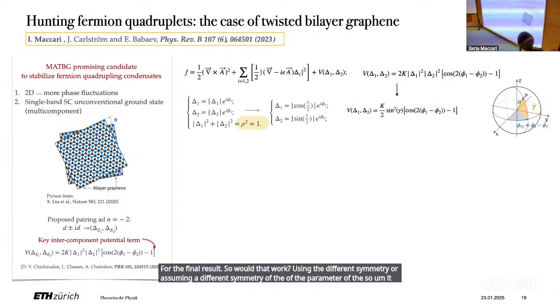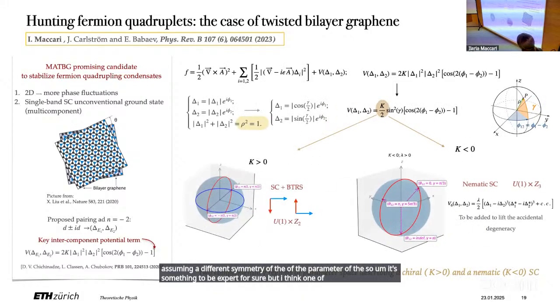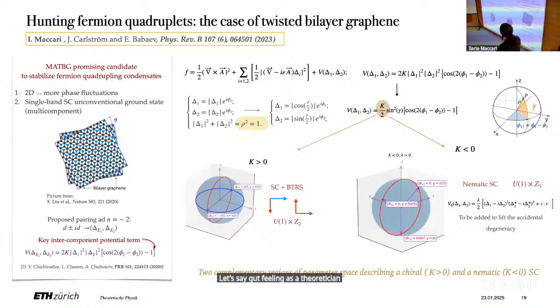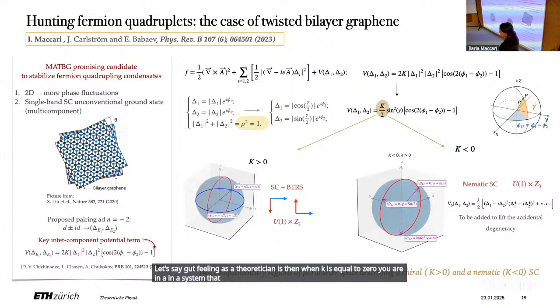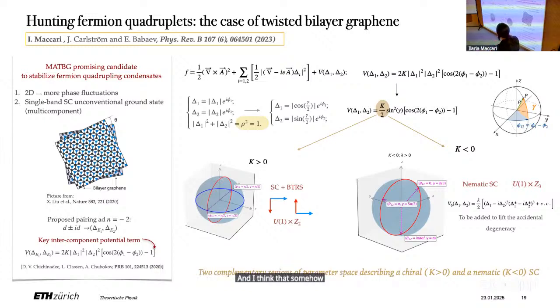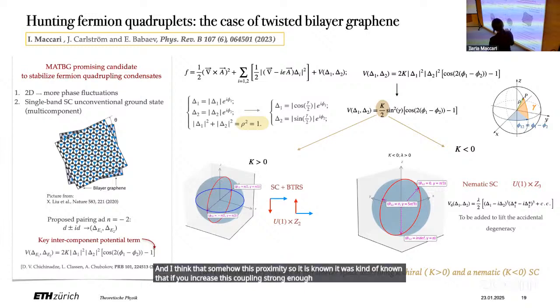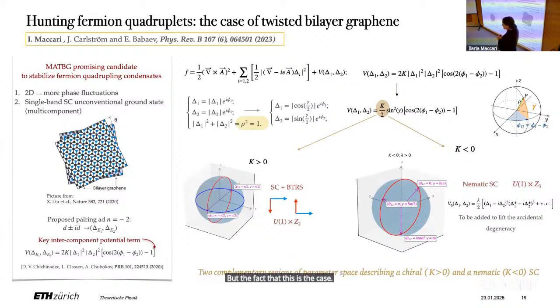It's something to be explored for sure, but I think one of the key things in this story, and this is my gut feeling as a theoretician, is that in this specific model when k is equal to 0, you are in a system that is fully symmetric, that doesn't have any phase transition, so the fluctuations are even stronger. It was kind of known that if you increase this coupling strong enough, at the end you stabilize the locking before the superconducting phase. But the fact that this is the case even when k is small, I think is due to the proximity with this supersymmetric point.